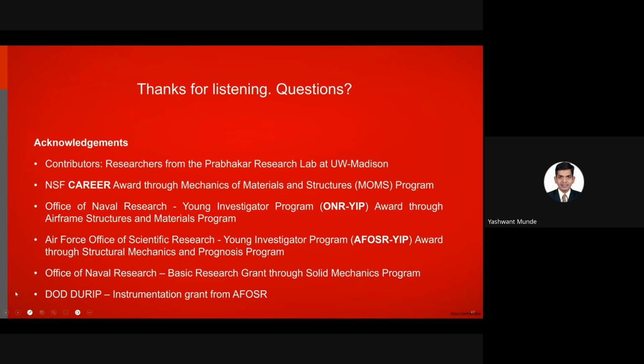Another question is, can any other thermoplastic be used for the foams other than TPU? Like I said, we have worked with collaborators at IIT Mandi, with whom we have looked at HDPE printing. HDPE is the one that we've used extensively to 3D print with hollow particles embedded in them. Now, the viscoelasticity has to be measured and studied for snapback. But if you're only interested in an architected foam core with microparticles embedded, then HDPE could be a potential thermoplastic.